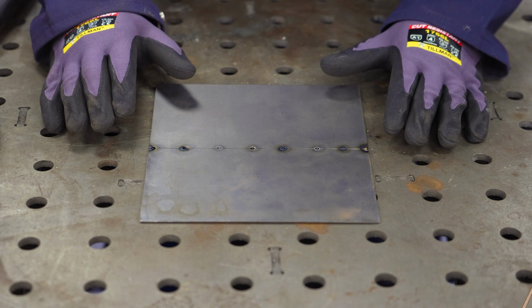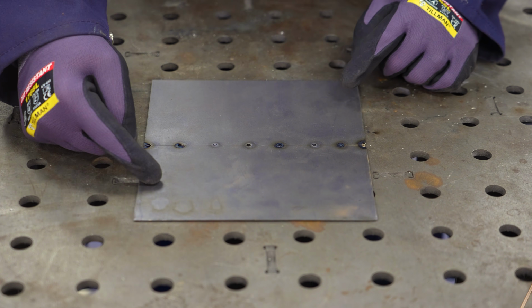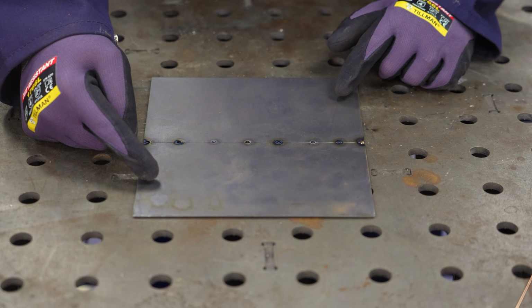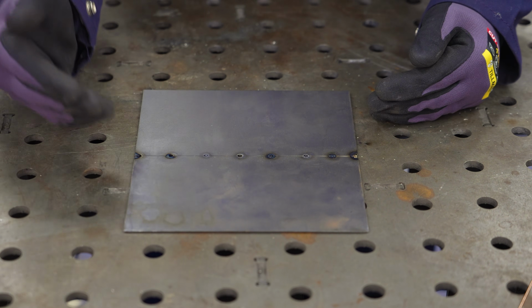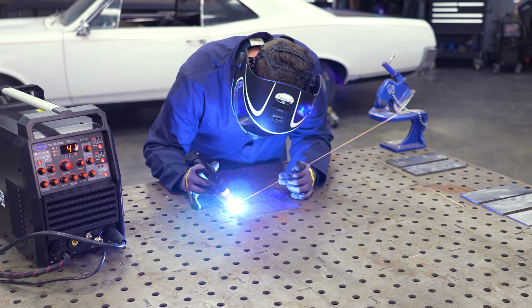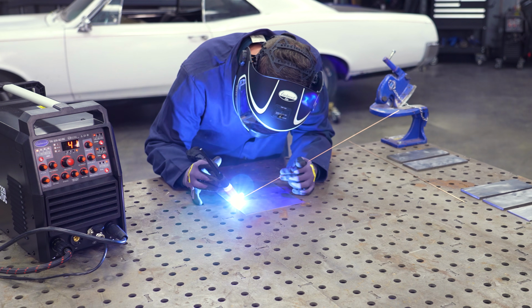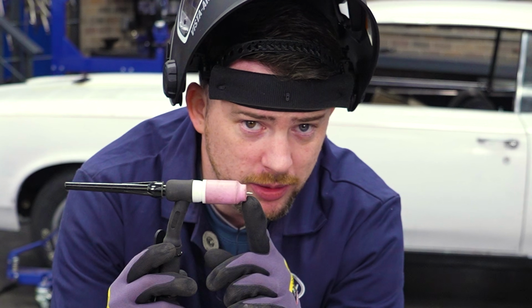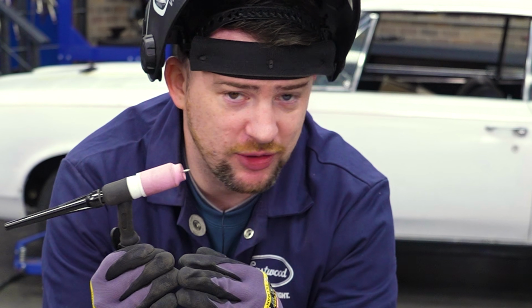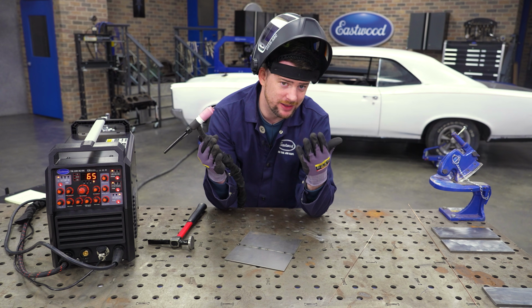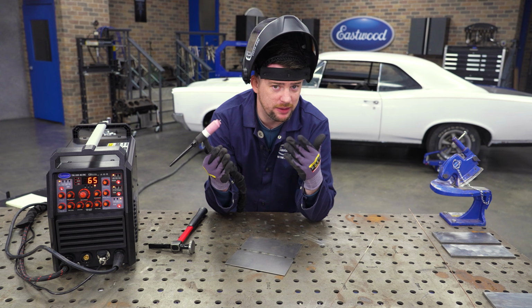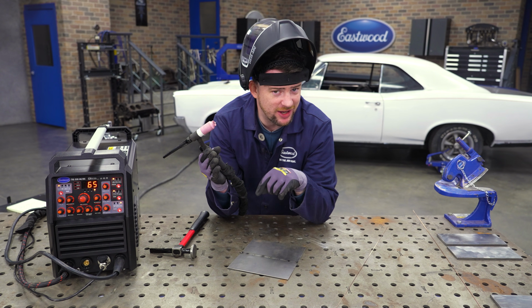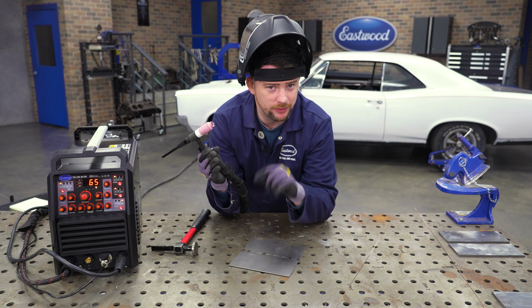So immediately, right off the bat, before I even hammered these tacks, you'll notice there's a little bit of warp, but it's way less than the previous way with the low frequency pulse. The reason for that is because a high frequency pulse gives you a much tighter arc cone, which gives you better penetration and it's not as wide, as opposed to the low frequency pulse, which gives you a really wide puddle, which is not particularly ideal for super thin sheet metal.